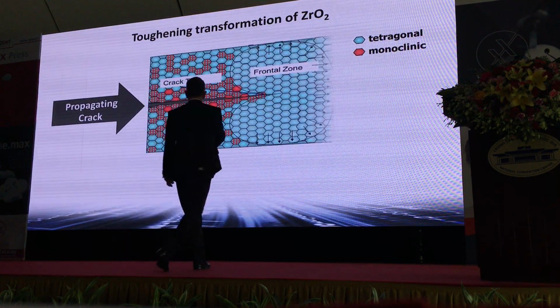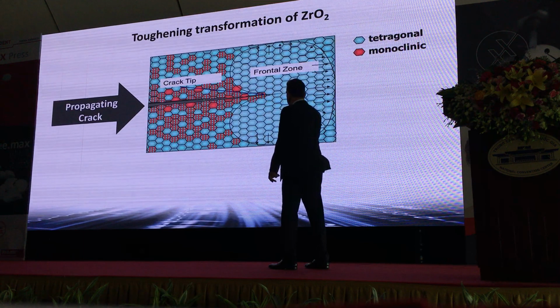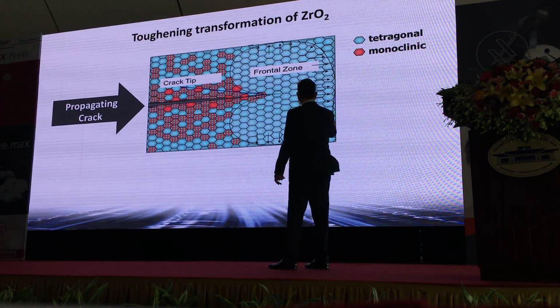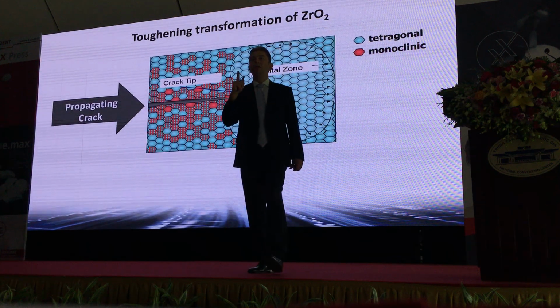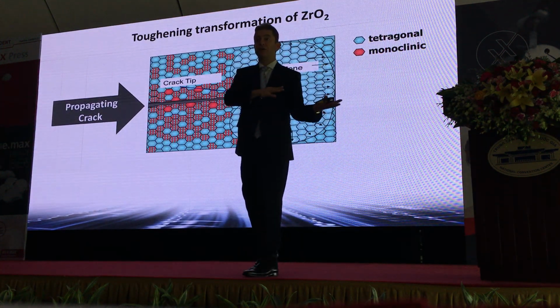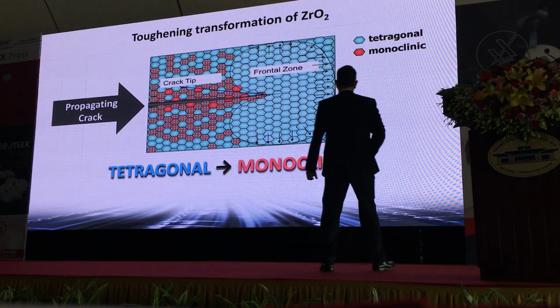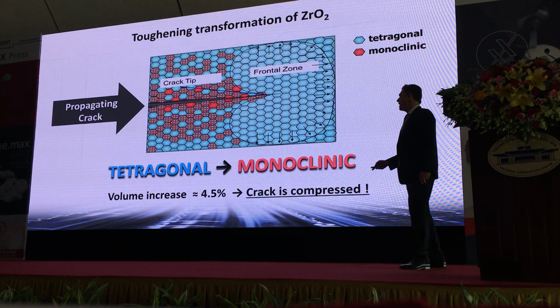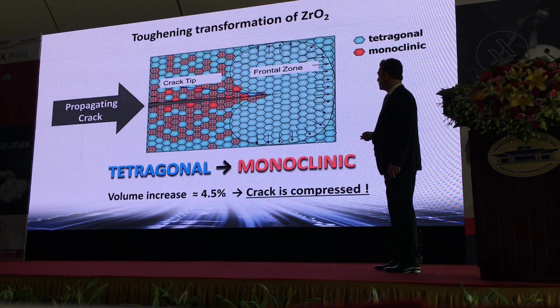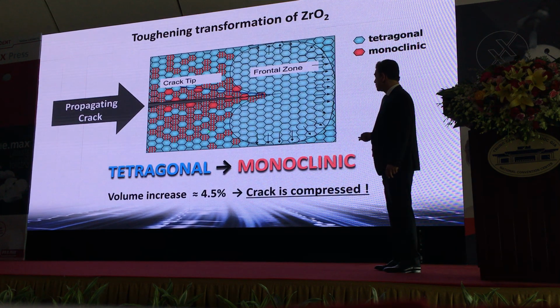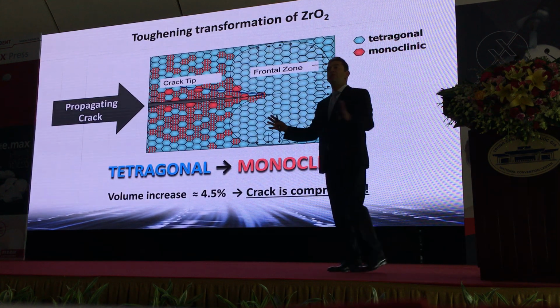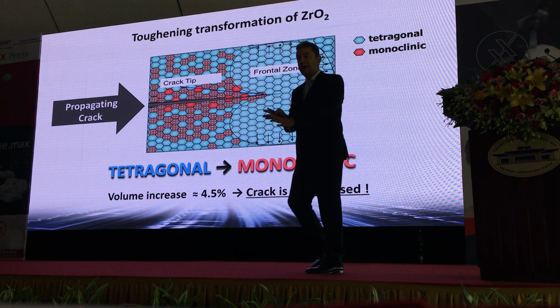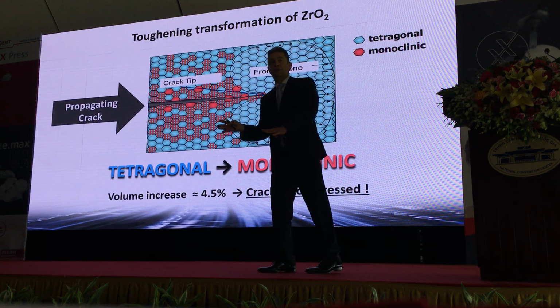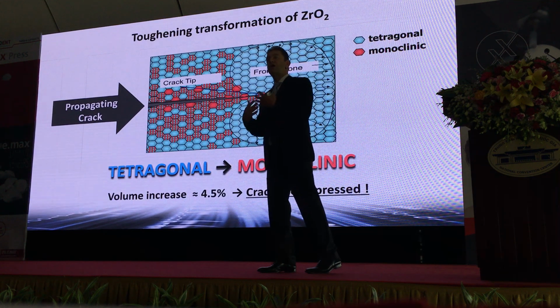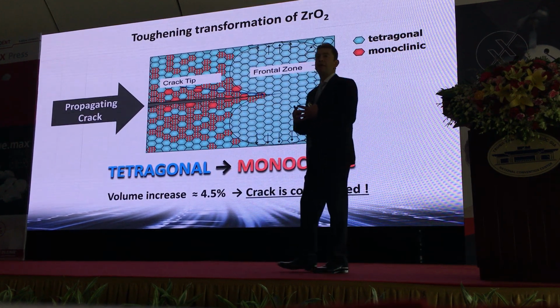Now if the crack is propagating through the material, you can see these tetragonal polycrystals change into monoclinic, and the monoclinic crystals are larger than the tetragonal crystals. So now we have a volume increase of 4.5%. The volume of the monoclinic crystals is larger than the volume of the tetragonal ones, and that's why the crack is stopped. The crack is compressed. So the crack cannot go further through, so we don't have a fracture. So this explains the much higher strength of zirconia compared to glass ceramics.